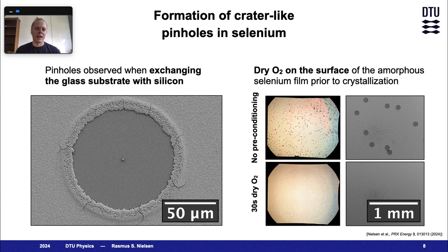For instance, the first challenge we encountered when exchanging our glass substrate with a silicon bottom cell was the formation of these large crater-like pinholes in the selenium thin film. Given that the silicon substrate is only a few hundred microns thick and exhibits a much higher thermal conductivity than the 2 mm thick glass substrates, the heat exposure experienced by the amorphous selenium film during the crystallization step will be much more abrupt through the substrate. We therefore had to re-optimize the crystallization step just to get a conformal thin film, which may negatively impact the optoelectronic quality of the selenium absorber.